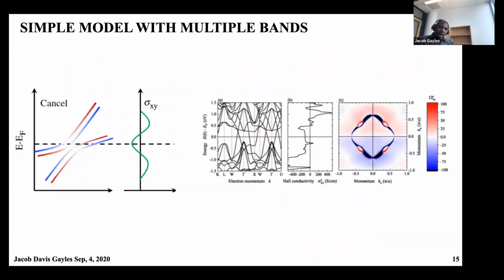materials. Now, in the other model, what we have is this material cobalt titanium tin, which is very similar to the Co2MnGa, but here, the cobalt and titanium show this cancel-out behavior, and you get a very small anomalous Hall effect. And here is to show the band structure that has Weyl points above the Fermi energy and the anomalous Hall effect, and the Berry curvature distributed in the momentum space, which has both positive and negative contributions.